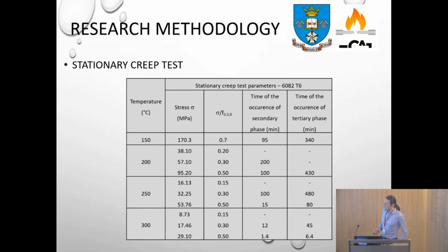As far as testing the creep properties of the aluminium alloy that we've taken, as Tom said previously, aluminium has problems with temperature in that the temperature interval in which the strength of the aluminium is reduced is far less than steel, roughly by half. So you have the onset of creep arriving really fast at approximately 150 degrees, and at 300 degrees you have a clear onset of creep. The secondary phase occurs quite fast if you look at the temperature of 300 degrees. So aluminium in general is very sensitive to high temperature, and it's also very sensitive to the development of creep as well. So this factor can also influence the reduction of the fire resistance time of any kind of aluminium structure.